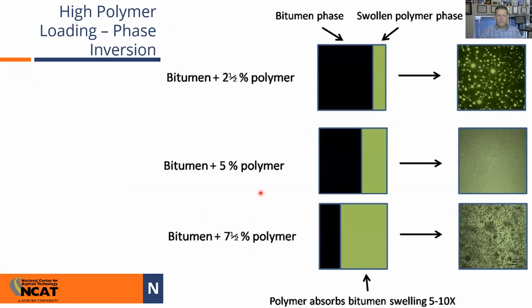So just to give you a very stick figure overview of how this works. At 2.5%, if you have asphalt and about 2.5% polymer, you have the asphalt phase and the swollen polymer phase. If you look at it under a microscope, in a micrograph like this, you have the polymers distributed in the continuum of asphalt. And that's true up to about 5% or so. But when you get up to 7.5%, or 7 to 8% polymer loading, you go through a phase inversion where the polymer swells and absorbs the asphalt. So now, instead of having, in the top picture here, polymer dispersed in asphalt, you now have asphalt dispersed in polymer. It really toughens the mix and fundamentally changes how the material behaves. Again, there's a lot of chemical engineering going on when you do this that I really don't have a very deep understanding of, but that's how it's been explained to me.